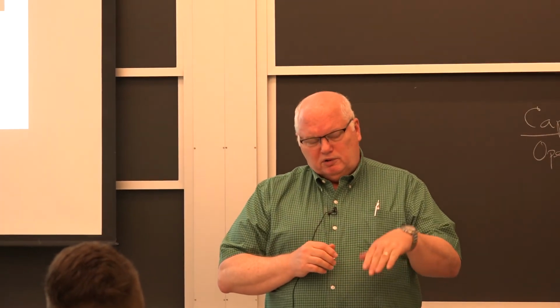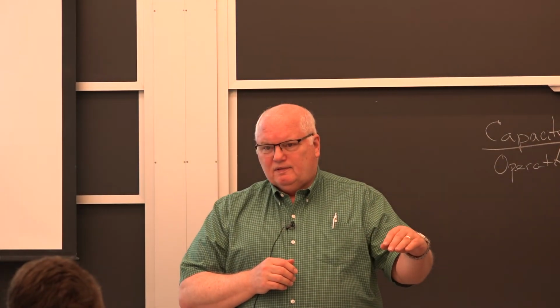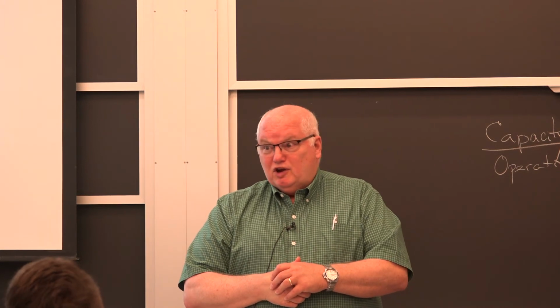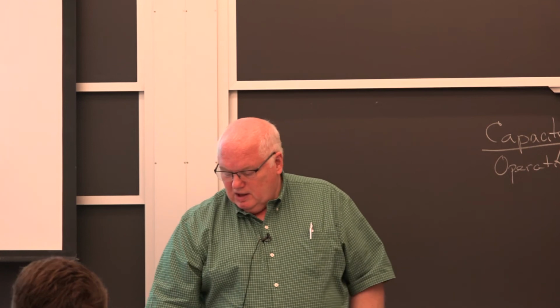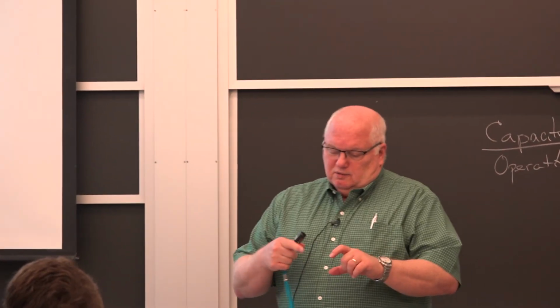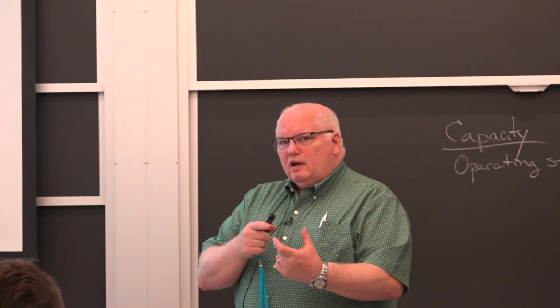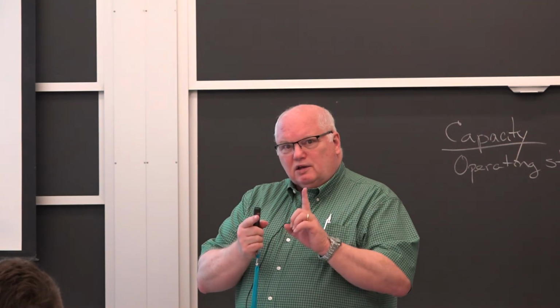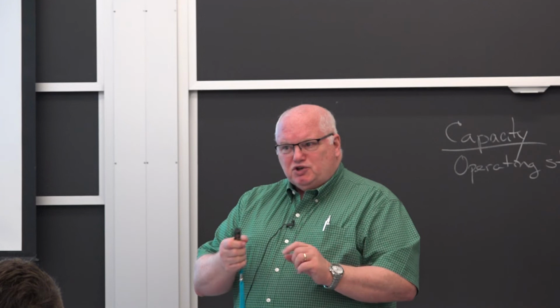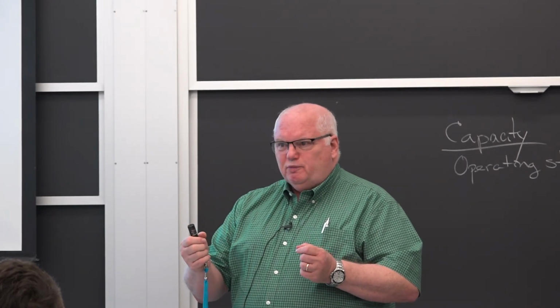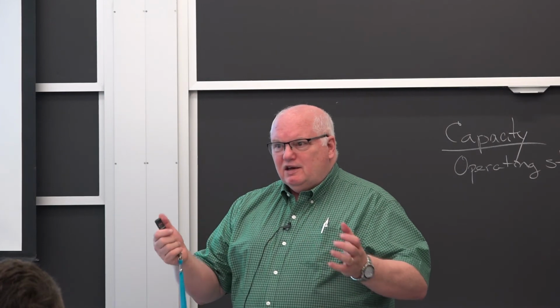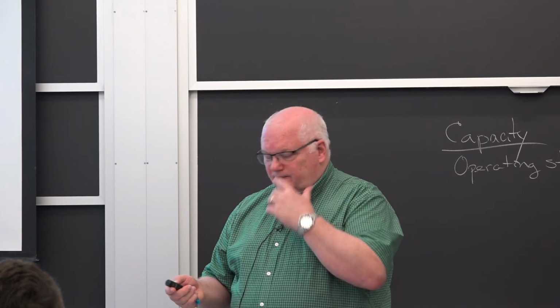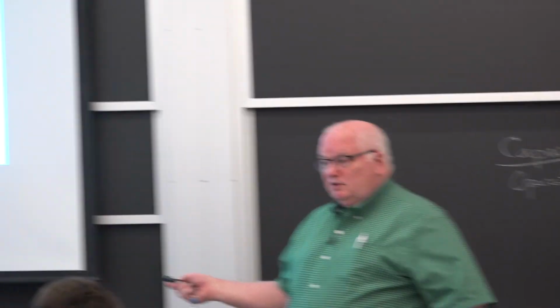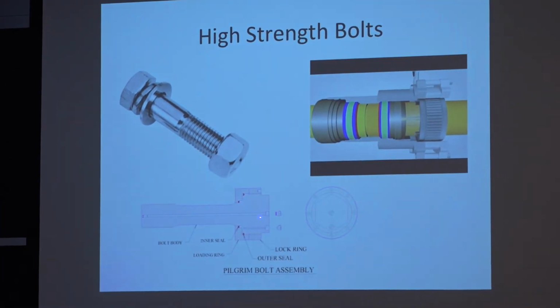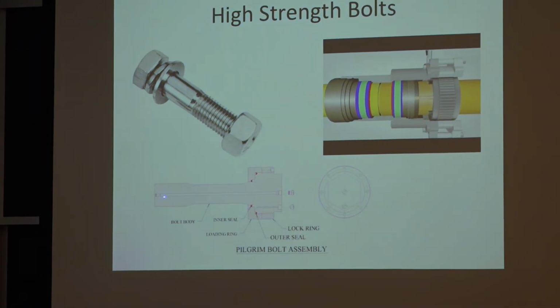To get good fatigue strength in the bolt, you want the bolt to be tensioned to 70% to 90% of its yield strength in order to get good fatigue resistance. And you got plus or minus 30% as your ability to do it. So in really critical applications, such as where I first saw it, on the crankshaft of an airplane engine, they actually grind the tip of the bolt and the bottom of the bolt to an exact dimension, and someone takes a micrometer, and this thing is 2.62 inches before they tension it, and after it's 2.68 inches. And so it's stretched 0.06 of an inch. And the stretch, Young's modulus, is pretty well known, and you can get down to plus or minus 10% of your stress in your bolt, which is what you really need.